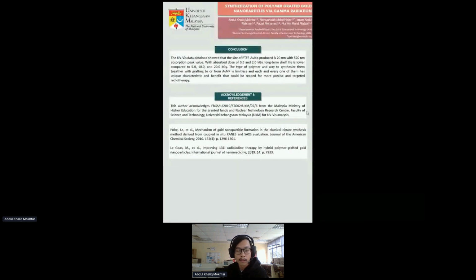For me, the conclusion is the UV-vis data obtained showed that the size of PVP gold nanoparticle produced is 20 nanometer with 520 nanometer absorption peak value. With absorbed dose of 0.5 and 2 kilogray, long-term shelf life is lower compared to 5, 10, and 20 kilogray. The type of polymer and way to synthesize them together with grafting to or from gold nanoparticle is limitless, and we can use other sorts of polymer to synthesize more precise and targeted radiotherapy. Thank you.